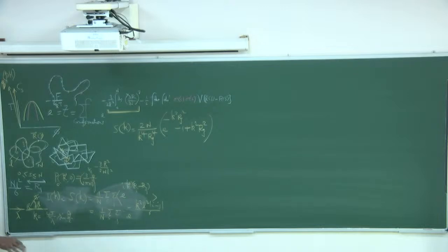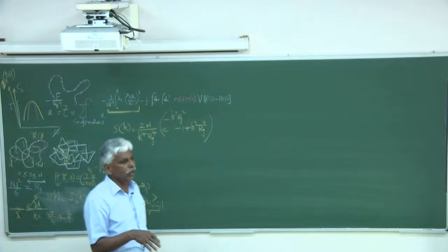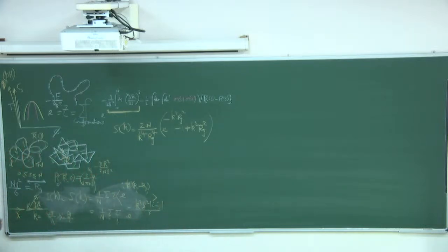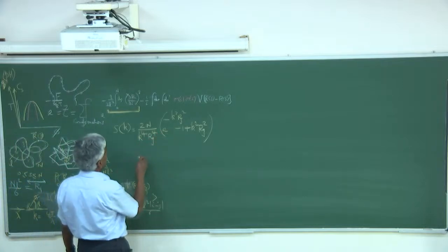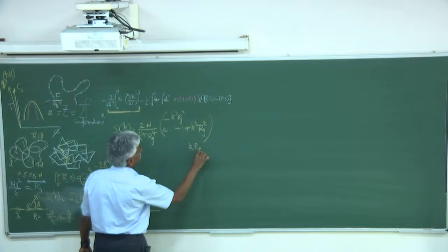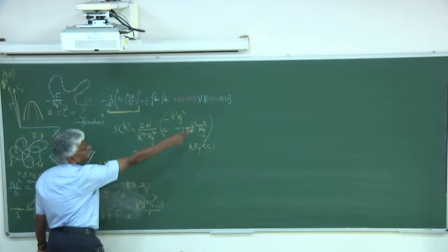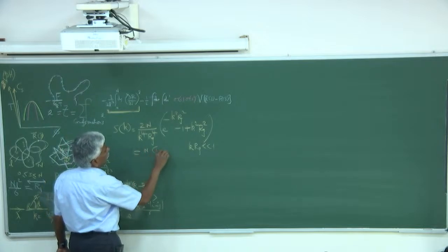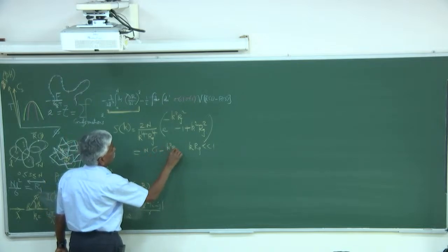When theta is small, sin theta is small, therefore k is small. If k is small, then this expression becomes like this, and you measure as a function of different k, and you get Rg, and then when you extrapolate for small values of k, you get N. So in a single experiment you can get N and Rg, the molar mass of the polymer, and also the radius of gyration.